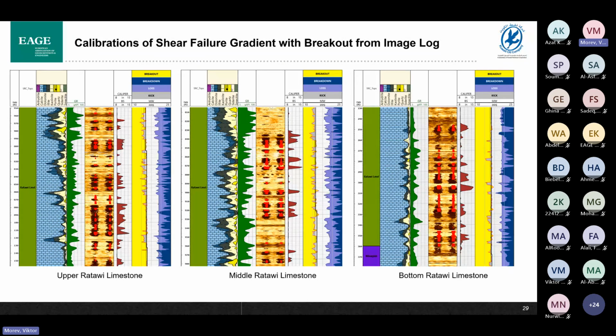Here we compare the predicted breakouts, which are the red patterns, with the real breakouts from the microimager in different parts of the Ratawi limestone. Here you see a pretty good match, and this is one of the ways to calibrate the geomechanical model and shear failure gradient. So at this point, once we trust the offset well model, we can make the key shift from explaining what happened in the past to predicting what may happen in the next well.